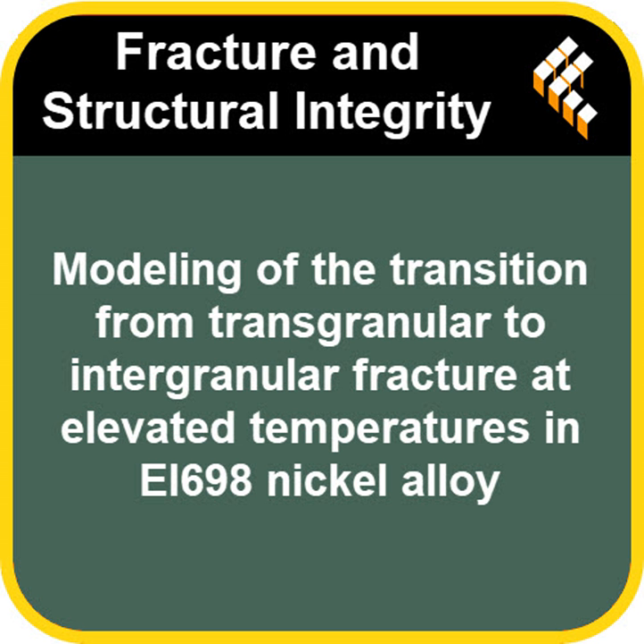Well, first off, validation. The model showed really good agreement when compared directly against experimental uniaxial stress-strain diagrams. The root mean square deviation was quite low, around 33 MPa, which is pretty good for this kind of complex simulation. So the basic material response was captured accurately.